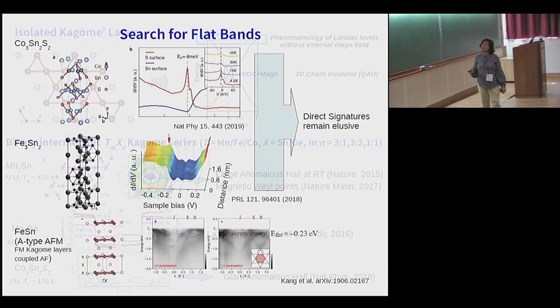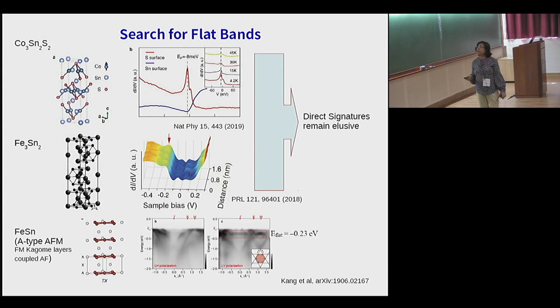Now, what about the flat band? There has been scanning tunneling spectroscopy done on both these compounds, which are actually ferromagnets, and there are signatures of this diverging density of states, but still the direct evidence of such a flat band remains elusive, because in addition to such 2D bands, there are also interfering 3D bands which are coming from basically the spacer atom, the tin or the sulfur.